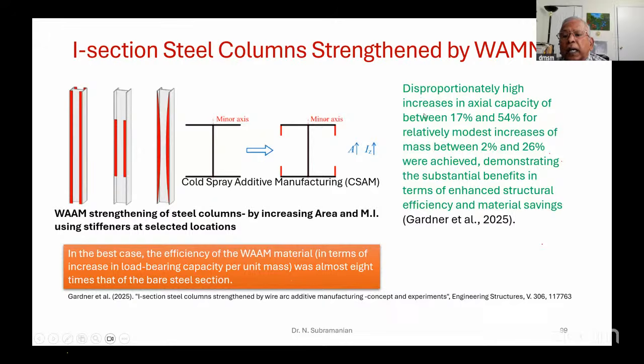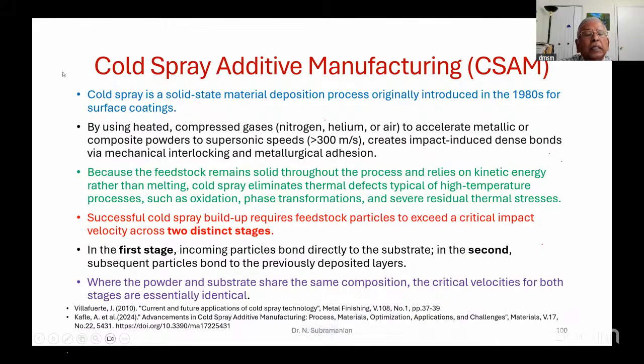It gives a disproportionately high increase in axial capacity of between 17 to 54% for the relatively modest increase of mass of between 2 to 26%. If you increase the mass by 2 to 26%, the capacity increases by 17 to 54%, demonstrating the substantial benefits in terms of enhanced structural efficiency and material savings. Of course, WAAM, I discussed it initially. I will just discuss the cold spray additive manufacturing.